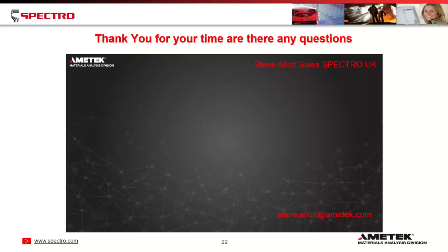Yes, for a spark system, it definitely causes problems with your results. It evaporates very, very quickly when the spark is created, so it will kill the spark. It will certainly give you the white burn spot, but it stops the emission of light, really. So it's really bad. I know in the past I've had water in a spark stand, and even though you dry it out and clean it, it's a good 2 weeks to actually get the system back to being able to measure samples down at the low trace level elements that you needed to measure. So you must dry the sample if you're using a spark system.